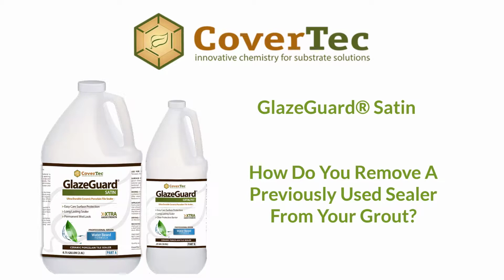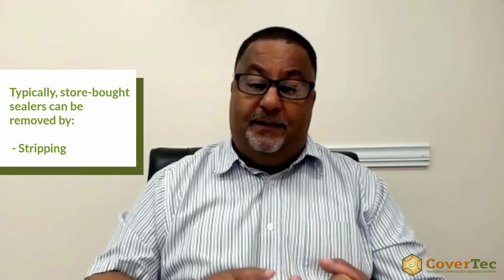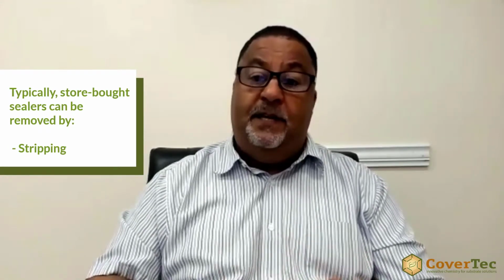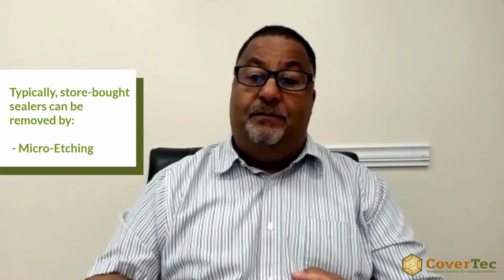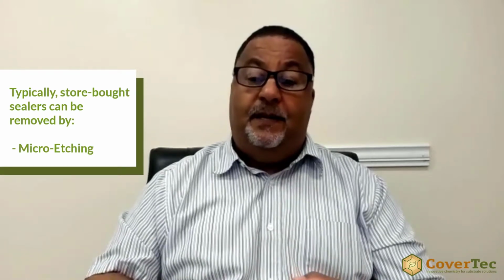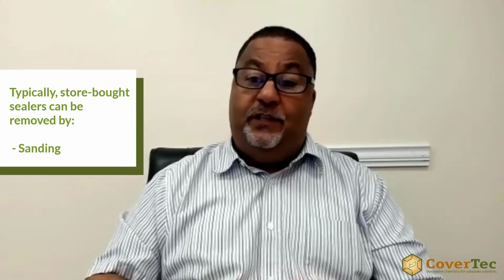So if your grout has been previously sealed and you want to then seal over it with the GlazeGuard Satin, you need to just check, first of all, with the grout manufacturer or the sealant manufacturer, how to remove that product. Typically, it needs to be stripped, using a floor finish stripper, or it needs to be etched with some kind of micro etching cleaner, acidic based, or it needs to be sanded so that we can top coat it.